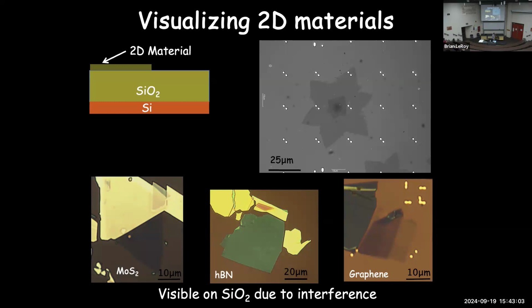And so these materials, even though they're only a single atom thick, or 3 atoms thick in the case of molybdenum disulfide here, as the light passes through them, if they're on a substrate, light comes down and reflects. Depending on the thickness, there's a little bit of a path length change for that reflected light, and therefore a slight change in the color or the absorption of the material, and that shows up as a change in the optical measurement that we look at.